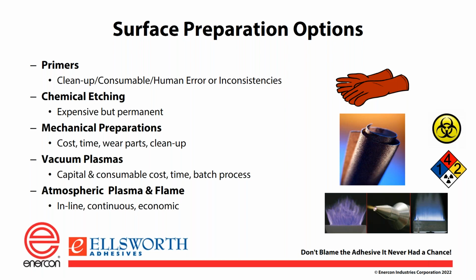And many times, the first three of these, the mechanical preparations, the etching, and the primers, they all are by hand in some form or fashion. And so that's less repeatable. So your standard deviation in your final product goes up. You have some poor product designs, you have some failures in the field, and if you move to a plasma or a flame type pre-treatment, you can predict more accurately what's going to happen after you do the bond.